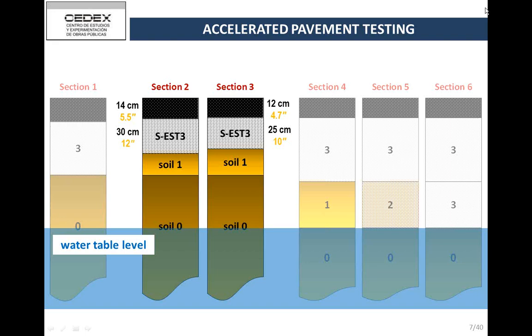Well, one of the things I'd be interested in doing, and it's one of the things I hope we're going to do here, is to change the model and add a layer to the back calculation at the interface, like a really thin layer, and then vary the strength of that with a full bond condition on both the upper and lower interface, and see if you can use the inner layer to capture the difference that you're seeing in your data. And Stefan, I think if you did that, then possibly you could capture the crumbling effect that you said y'all observed in Louisiana. Well, we saw the crumbling effect in the forensic analysis, and then we said, let's assume there is a layer that is very weak between the asphalt and the soil cement. We did back calculation and forward calculation, and we found that you lose significantly in the fatigue life of the section once you lose the bond.